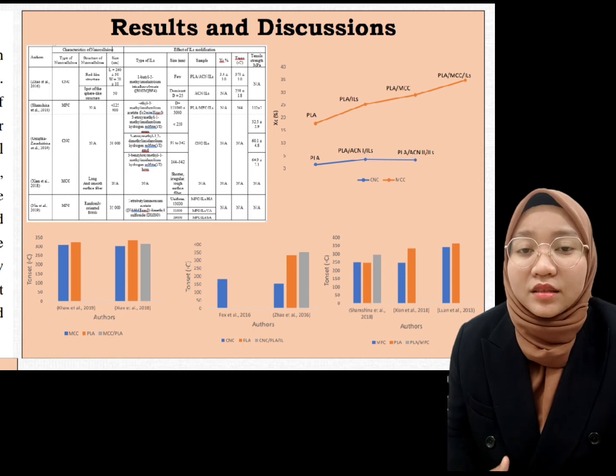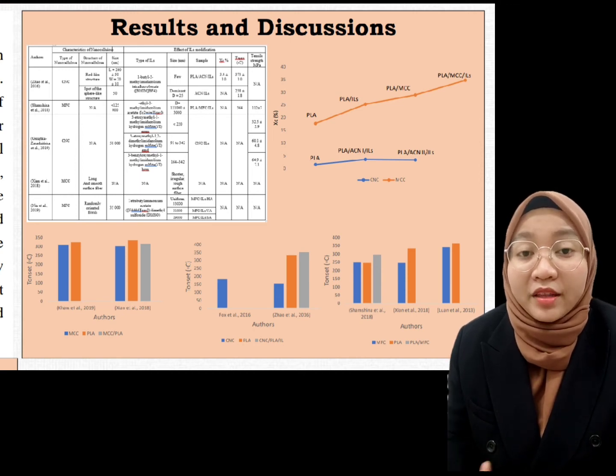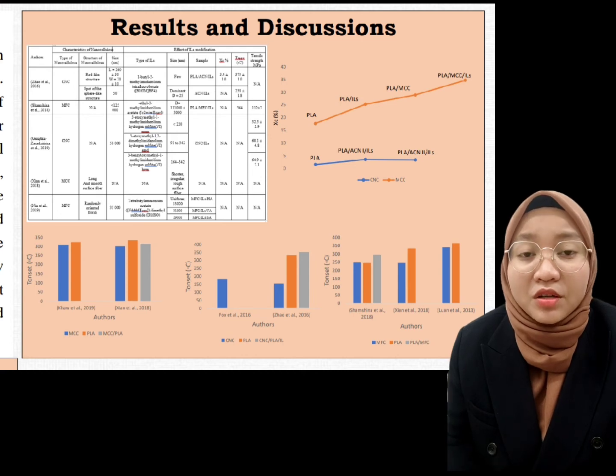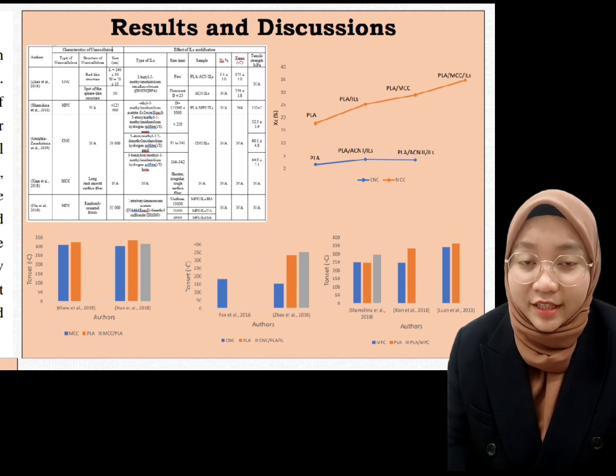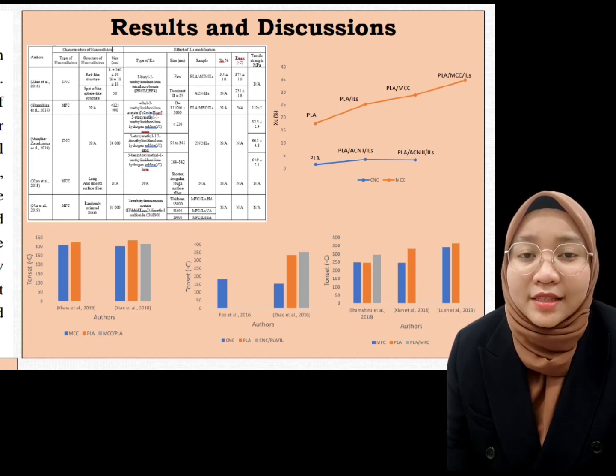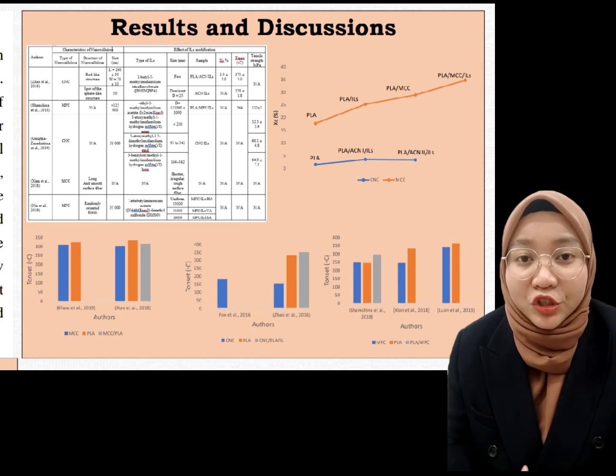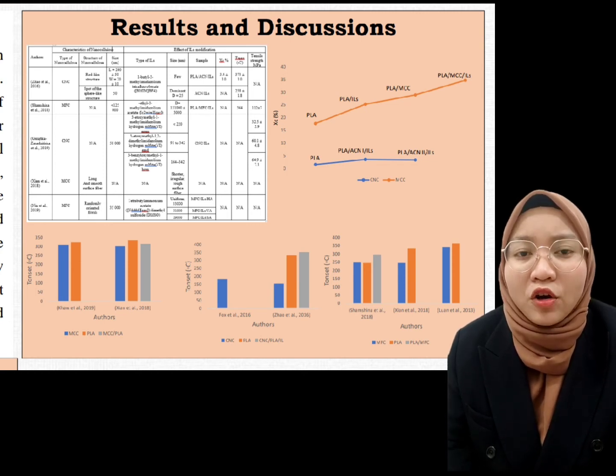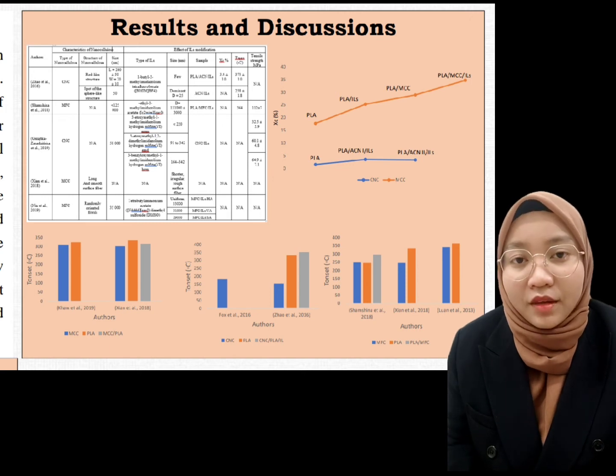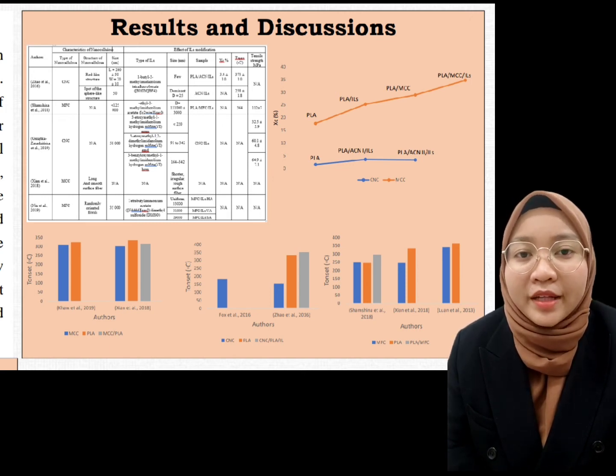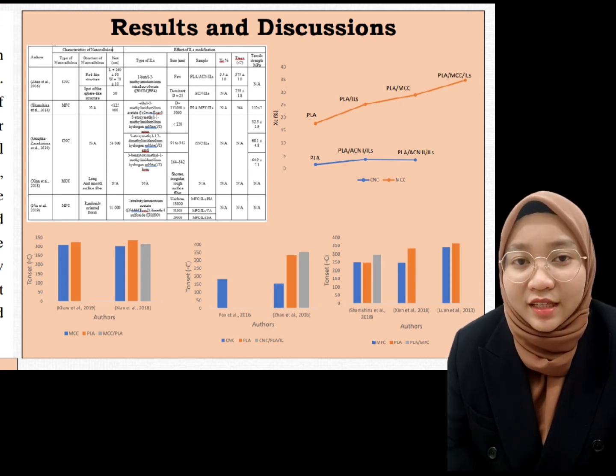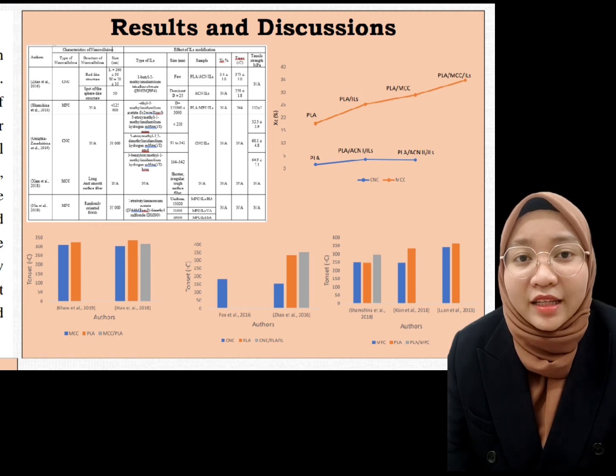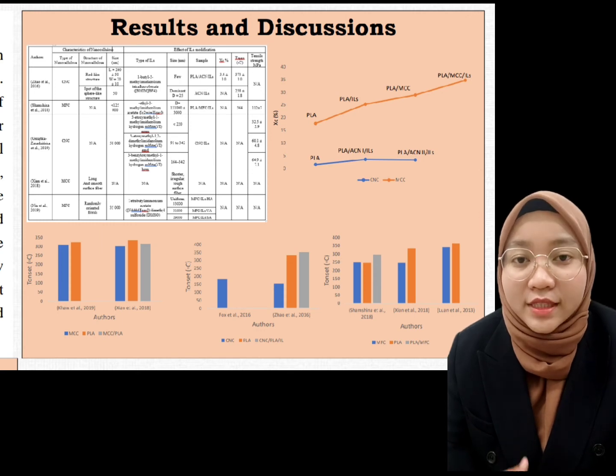Next, the greater the T-onset and Tmax, the better thermal stability. When the temperature rises, it was more likely to degrade. The T-onset rose as the length of the grafted PLA chain grew longer. Incorporating cellulose or nanocellulose with PLA blends, thermal stability has also been significantly increased. Because of the high interfacial adhesions, the biocomposite thermal stability was improved.